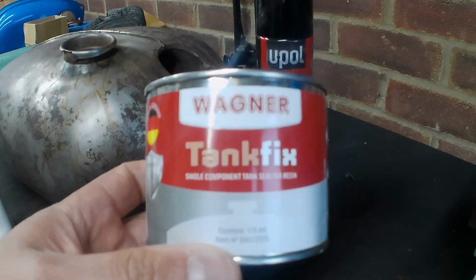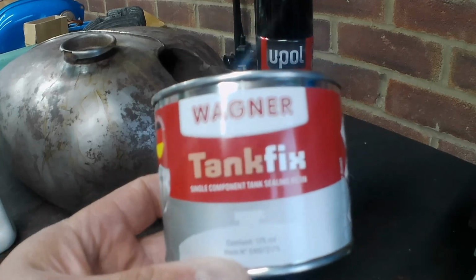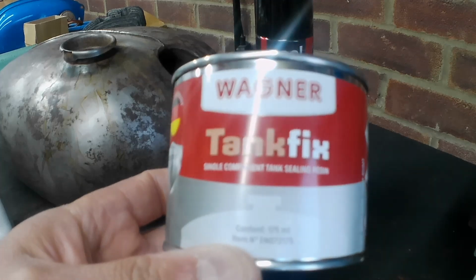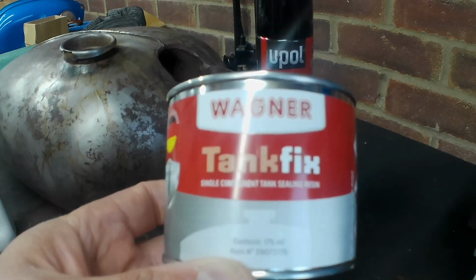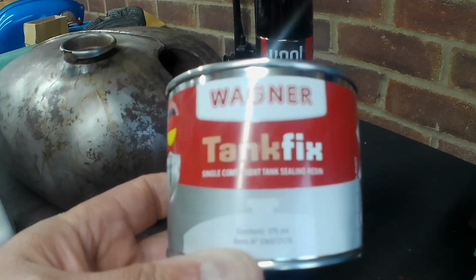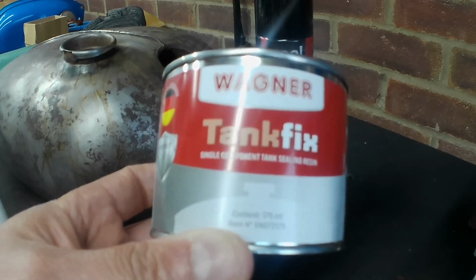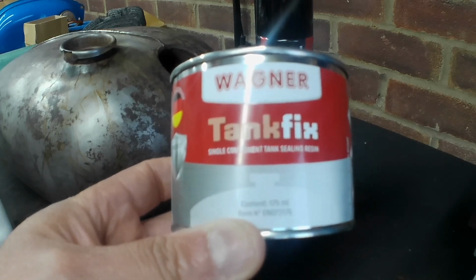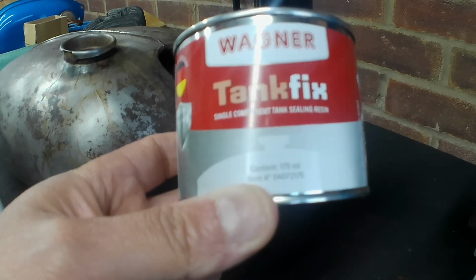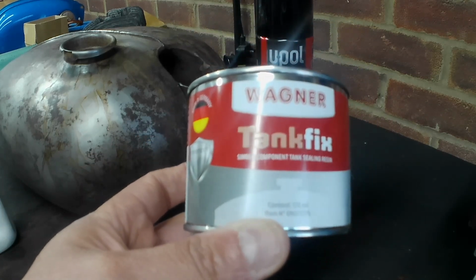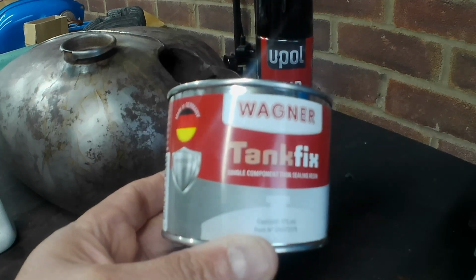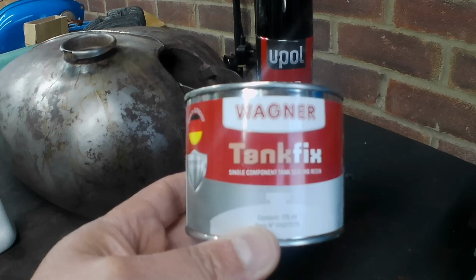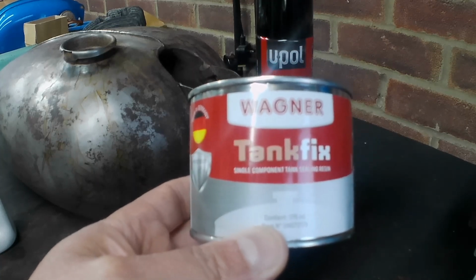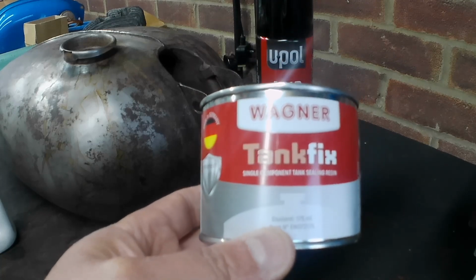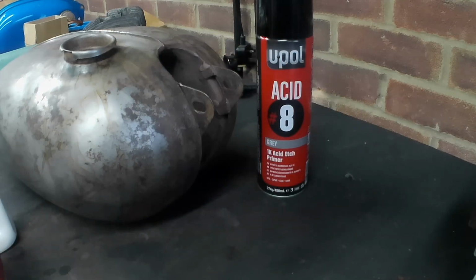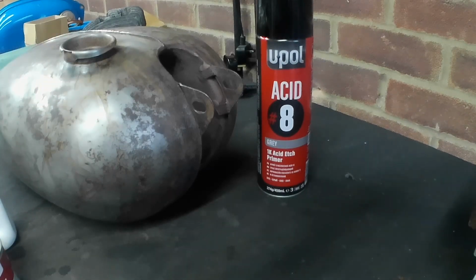And very simple to use. Basically, once the tank is nice and clean, you pour this stuff in, you sluice it around, you get it over every surface. You have to take some pains to get all of the excess sealant out. You don't want it pooling. And then you keep that in a sealed jar. 24 hours later, you do exactly the same again, only this time you leave it for 7 days. And the humidity in the air actually kicks off the curing process. So, as I say, I've used it before and had good results. And the good thing about this stuff is you can use it with premix, two-stroke premix, and some of the other sealants out there you can't. So be aware that not all are suitable for our premix bikes.